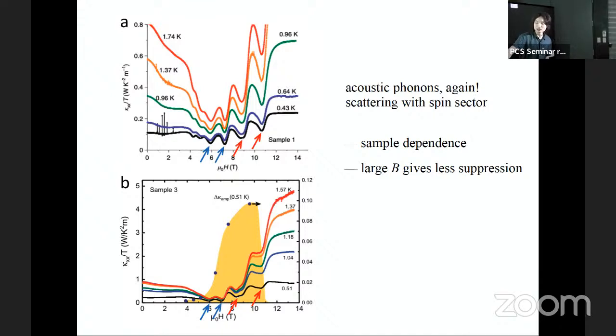is that in the intermediate magnetic field, the kappa is smaller than at large magnetic field. At large magnetic field, the spins are all frozen in the direction of the magnetic field, so the spins are doing nothing. In that case, the kappa is larger. And moreover, in the large magnetic field, you can see it goes as the T cube of the phonons. So what does this suggest?